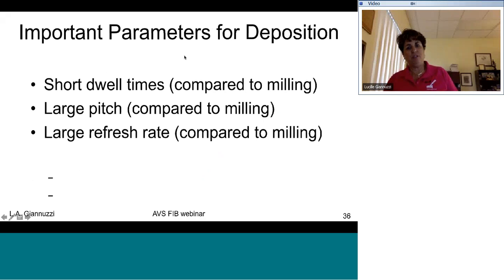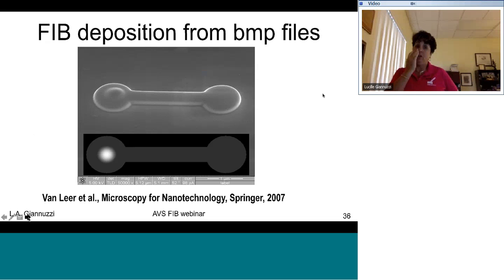So important parameters for deposition: you want very short dwell times compared to milling. This is because you don't want to mill through the gas. You want a chance for the gas to replenish itself. You want a very large pitch compared to milling, so generally this is going to be 0% overlap or larger, more negative. And you want a large refresh rate, again, because you want a chance for the gas to adsorb back onto the sample surface before you hit that pixel again. You can also FIB deposit from bitmap files.